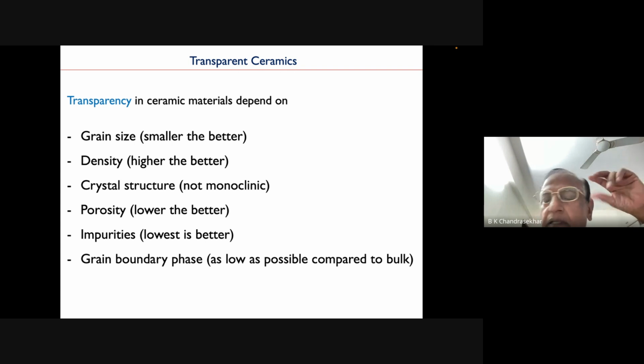What it means is that you press the material to a very high pressure, and at that pressure only you increase the temperature to a very high temperature. Therefore the porosity is completely eliminated and the sample becomes transparent. Sometimes it is translucent, it may not become completely transparent, but it can become translucent. In such applications, the grain sizes are very, very small, and density is much better.